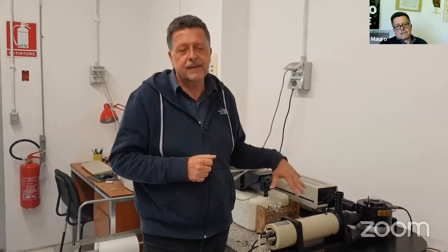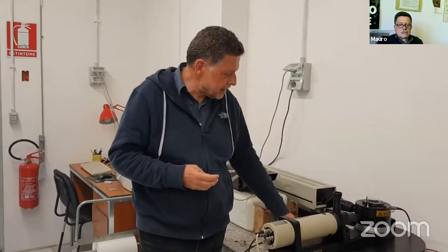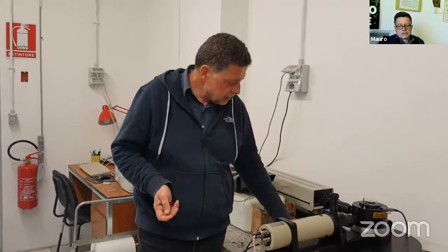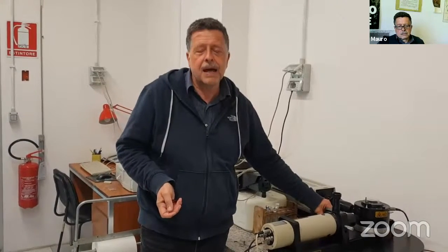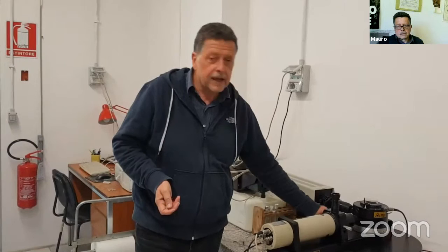Because the smaller the particles, the faster their movement. So by analyzing the velocity by which the scattered light changes, you can go to the particle dimension in a suspension. And this can be done for very small particles, down to a few nanometers. So you can measure the hydrodynamic radius of very small particles in their medium without using an electron microscope. Okay.